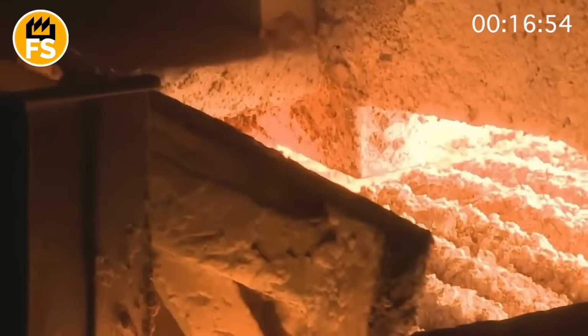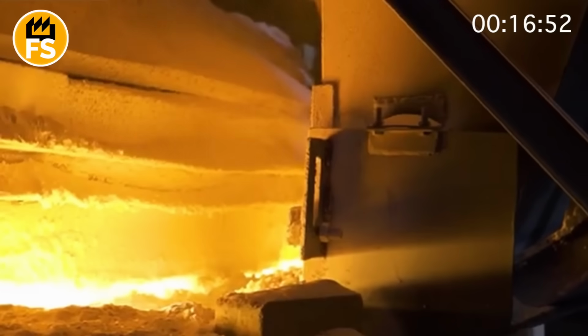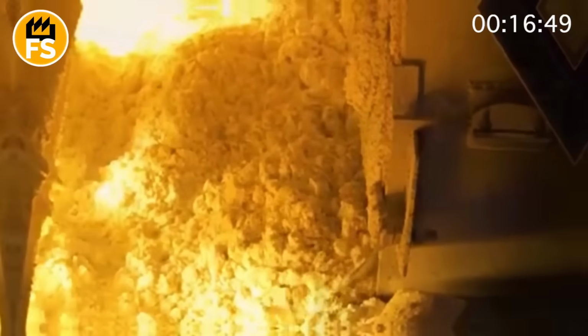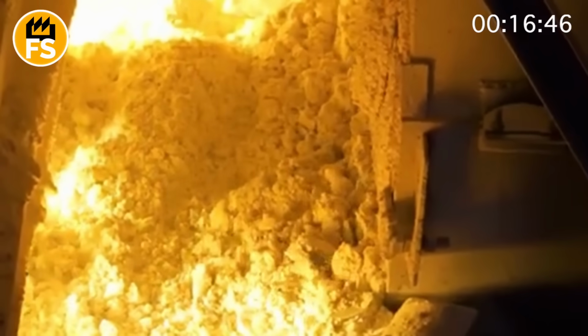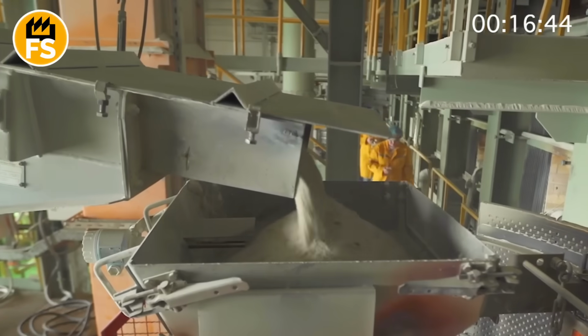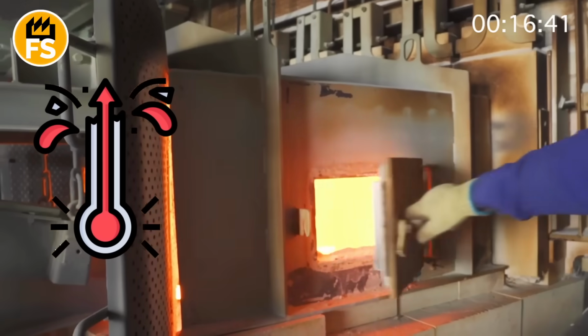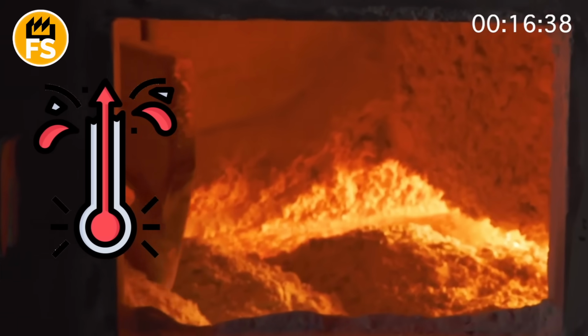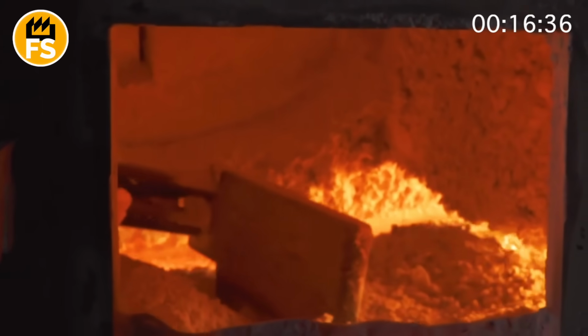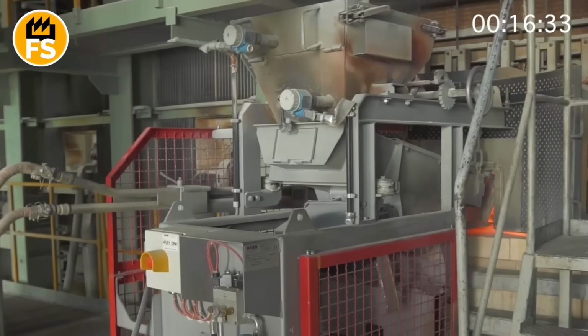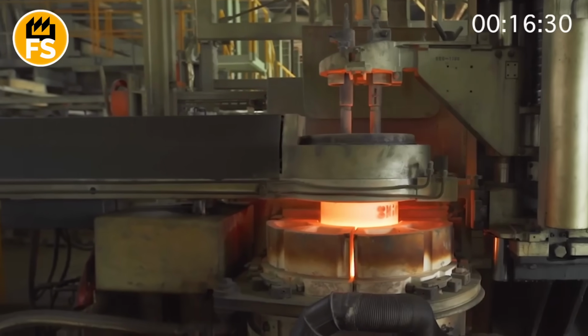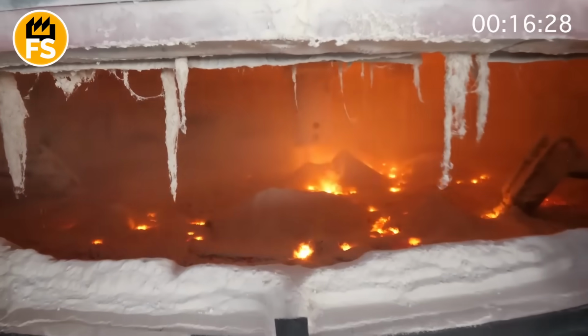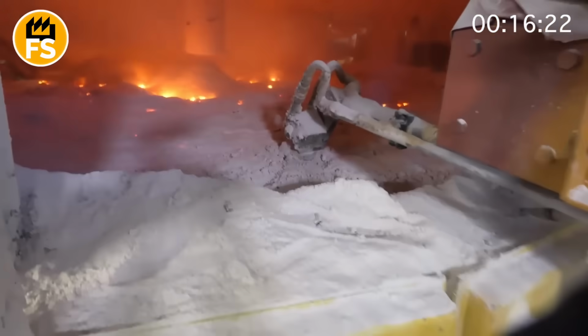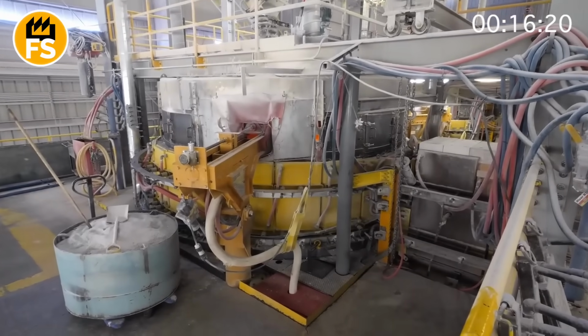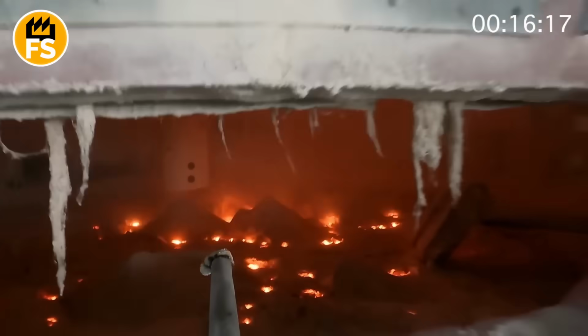The mixture, having just completed a complex journey from the quarry to the mixer, finds itself at the heart of production, the glass melting furnace. This is a true industrial volcano, over 200 feet long, with a temperature of up to 2,900 degrees Fahrenheit in the melting center. There's no open flame here. Only walls of refractory brick heated to white hot and gas burners that maintain the temperature with degree precision. The raw material is fed automatically, precisely dosed, several tons per hour. In the first 30 or 40 feet of the furnace, melting occurs.